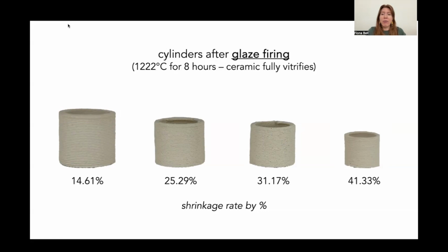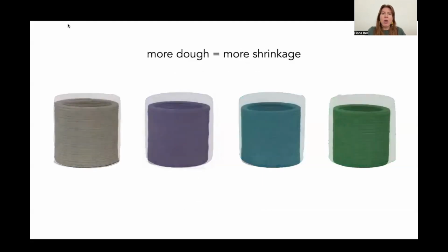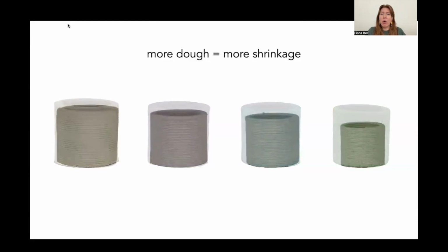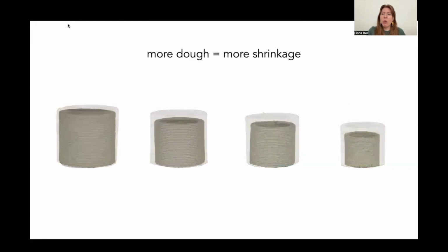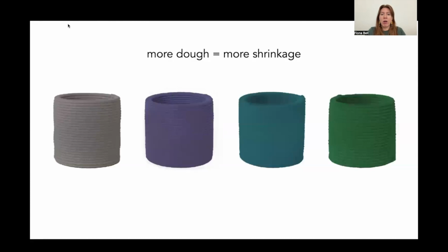Lastly, we glaze fire the cylinders. Glaze firing happens at a higher firing temperature and is the phase in which the ceramic fully vitrifies, meaning that it gains a more glass-like and crystalline structure. After this stage, the material reaches its final maximum amount of shrinkage. Through this test, we ultimately correlated the amount of dough to the amount of shrinkage that occurs.